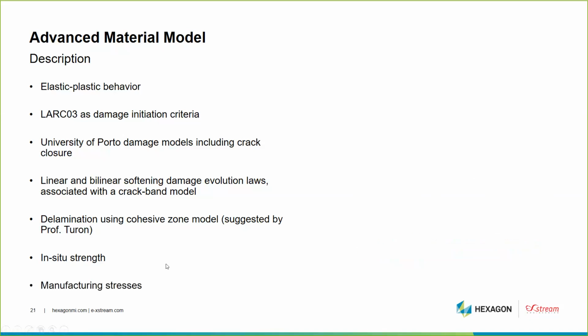And then the last feature corresponds to the possibility to take into account manufacturing stresses. So this is a feature that we added to take into account stresses, or residual stresses, coming from the curing cycle. So it means that before we load the coupon mechanically, we apply a thermomechanical load from the curing temperature to the room temperature in order to introduce some residual stresses in the coupon before the mechanical loading. And this is done now systematically once we use this advanced failure model.